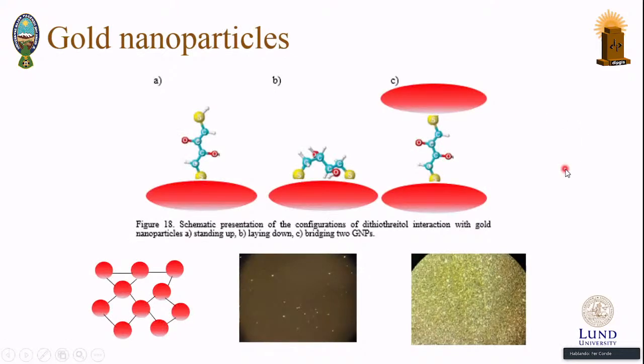Another way to increase the surface area for the detection of the aflatoxins was the use of gold nanoparticles. These gold nanoparticles are characterized by negative charges caused by the citrate compound. And we are using a dithiol in order to generate gold net formation. The configurations that this dithiothreitol can have are standing up, lying down, and forming bridges between gold nanoparticles. But as I said before, the negative charges between these gold nanoparticles must be reduced. So we are going to use sodium chloride to decrease this repulsion between the gold nanoparticles and get a net formation.